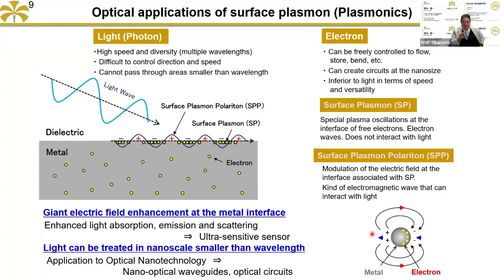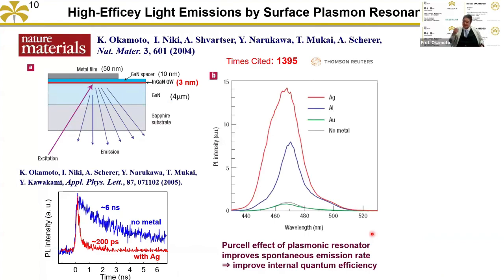Then, there are several application methods, but I think that with surface plasmons, the coupling of the electron and photon becomes strong. That's why I think the energy conversion between the electron and the photon must be increased. Then we tried to use that to improve the emission efficiency of light emitting material. Then we succeeded. We published that in 2004 in Nature Materials. Recently, many people know that surface plasmon resonance is useful for light enhancement and high emission efficiency. But that was the first experimental result. And that method is very easy.